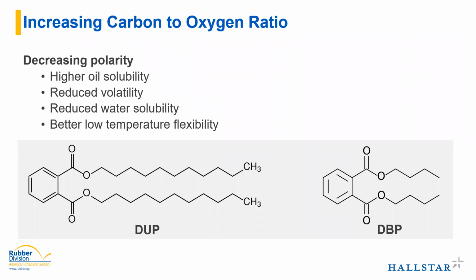So by adjusting the number of carbons that we have in the molecule, we can adjust the polarity of the overall molecule. If we increase the carbon to oxygen ratio, shown here with the diundecyl on the left with a very long carbon chain versus the dibutyl on the right with a very short carbon chain, that increases your carbon to oxygen ratio and decreases the overall polarity of the ester. When you decrease polarity, you see a higher oil solubility.